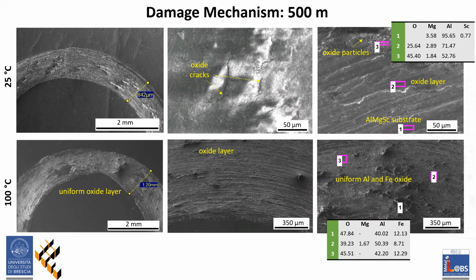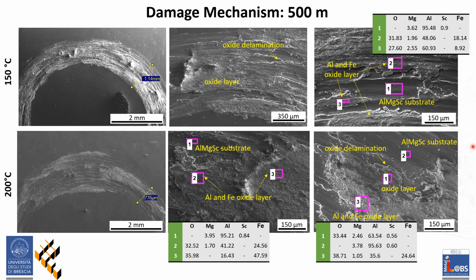Finally, the following two slides show SEM analysis after 500 meters at the end of the test. At room temperature, oxide cracks form, promoting the oxide layer fracture and the oxide particle formation, as can be seen from the images above. With temperature increasing, the aluminum oxide previously detected for the 100 degree case turns into aluminum oxide mixed with iron, which derives from the counterpart. This can be seen from the spectra reported. As can be observed, the iron percentage increases as temperature increases.